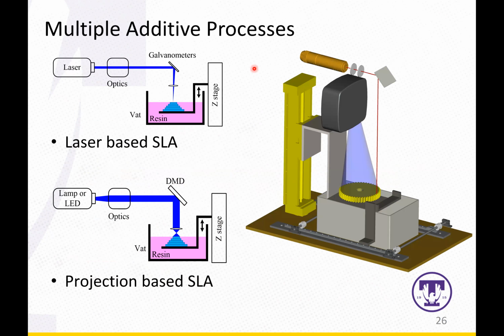Or in this case, as I mentioned before, there are two different types of stereolithography process. One utilizes a laser beam to cure the material. Another one uses a projected image to cure the material. One benefit of using laser is that the size of the laser spot can be controlled precisely. At the same time, the resolution of the projection-based SLA is limited by the pixel resolution.